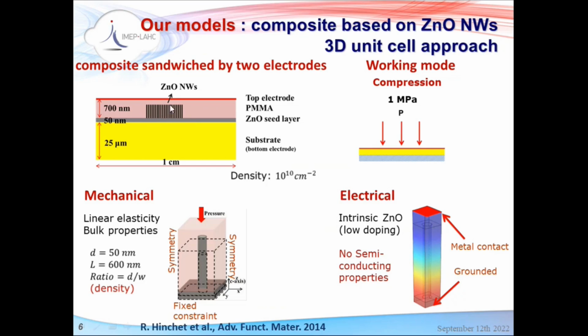So you can imagine that simulating billions of nanowires in this kind of composites is difficult. So we simplified the models, and we considered only one nanowire immersed into the dielectric, but with boundary conditions, because we solved this by finite element methods. So you have differential equations, boundary conditions, initial conditions. So you can make your models so that this individual cell is surrounded by others, by adding symmetry. So as I was saying, no semiconductor properties so far. And then we consider that we apply a pressure, as I explained before.